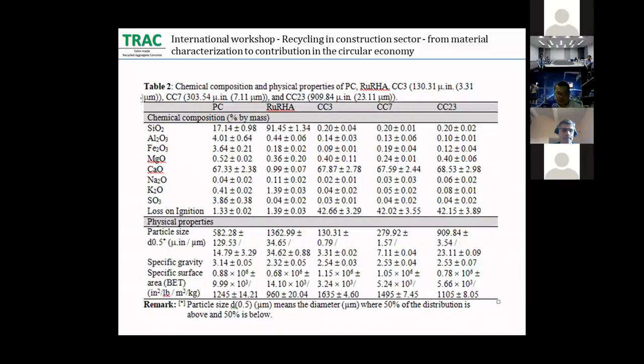The main components of the rice husk ash are high silicon dioxide and low calcium oxide. This table shows the physical properties of the particle size, specific gravity, and specific surface area of rice husk ash. Calcium carbonate obtained from a calcium carbonate plant in Thailand was used to replace Portland cement at percentages of 0%, 20%, and 40% with no processing or treatment. Three different sizes of CC were used: CC3, abbreviated for three micrometers, CC7, 7 micrometers, and CC23, with a particle size of 23 micrometers.